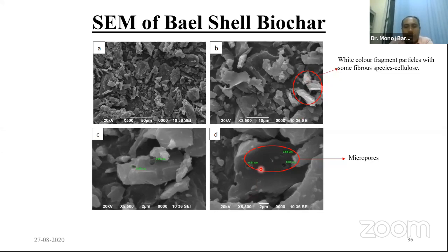And if we see at a very high resolution, such as 5500, we can observe some pores of very small size, for example 0.54 micrometer or maybe 0.83 micrometer. So this is how at a very high resolution we can see some porosity on the surface of the Bael Shell biochar. This porosity has a very significant role if we apply it for some agricultural purpose, because if there are pores, it may be very useful, as it can absorb water and so on. So this is how we can do various analyses with the help of these SEM images.